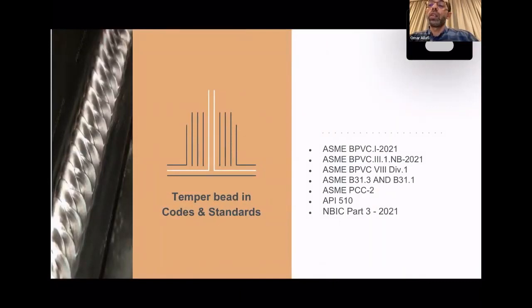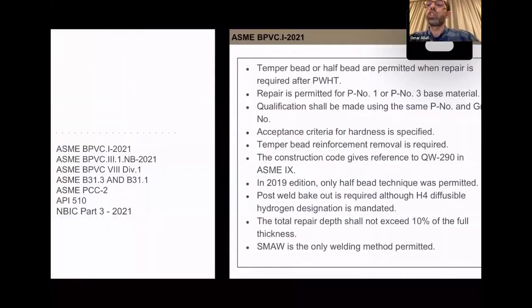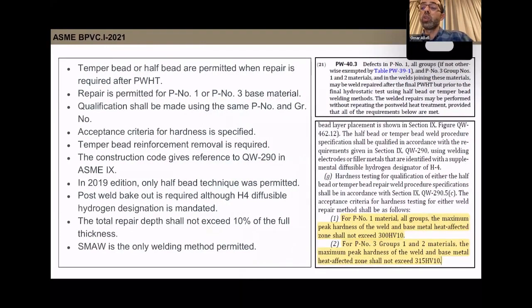Codes and standards, and I will start with Section 1. In Section 1, the only method recognized by ASME was the half bead, but in 2021 they changed and they're accepting both half bead and temper bead. And this is, I think, the only code where it specifies an acceptance criteria for hardness, and it is only allowed for P number 1 and P number 3 material. This is, of course, after the PWHT.